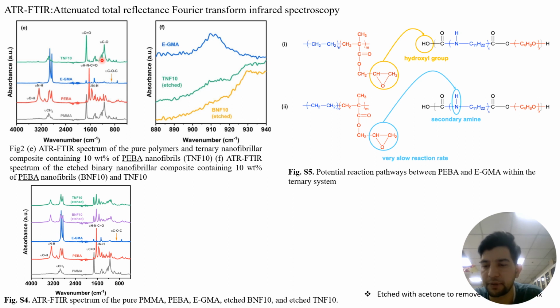So this shift can be attributed to the formation of hydrogen bonding, which weakens the NH bond and causes a decrease in the vibration frequency, resulting in the observed red shift in the peak.